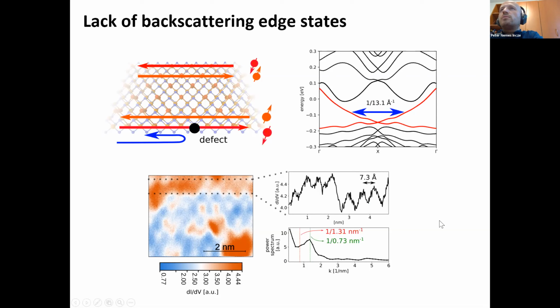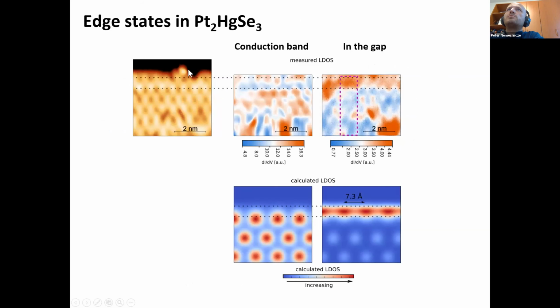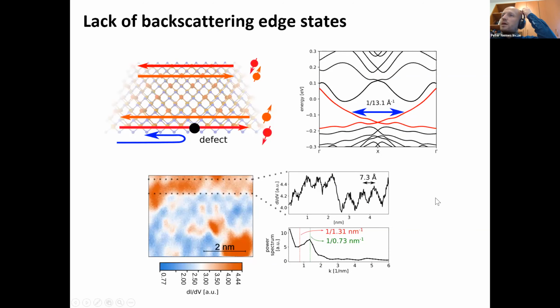Of course, it's always hard to prove the absence of something. It's easier to prove the presence of something, but here we try to prove the absence of backscattering. But nonetheless, STM is well known to show basically interference patterns of trivial electronic states around defect sites. So what happens is basically your electron comes in, gets scattered by a defect. For example, here, this small notch or this small adsorbate here at the edge, it can scatter your electrons. And this results in a standing wave in the local density of states, which STM is very sensitive to.